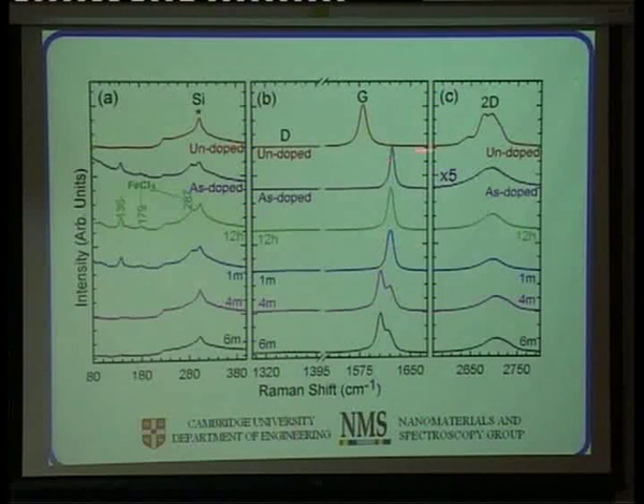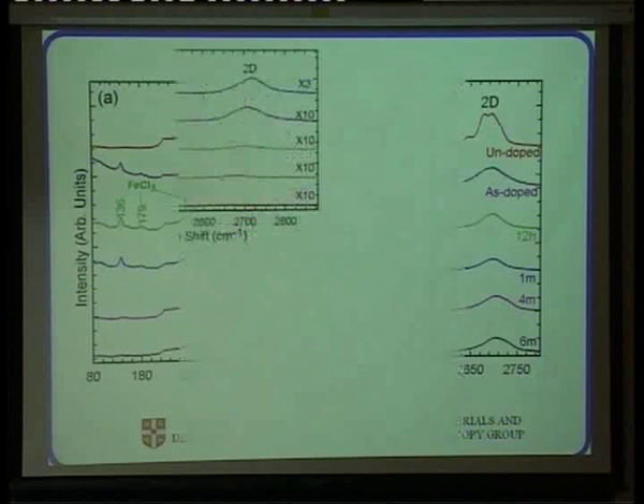And if you're not very careful, or if you leave it in air for a large period of time, there is some desorption of the intercalant, and you can get, for example, the splitting of the G peak, which is known when you have a non-uniform doping in the sample. Okay, this is some sort of background here.